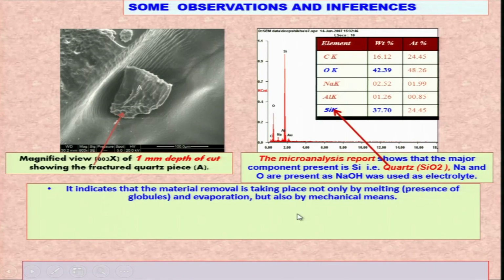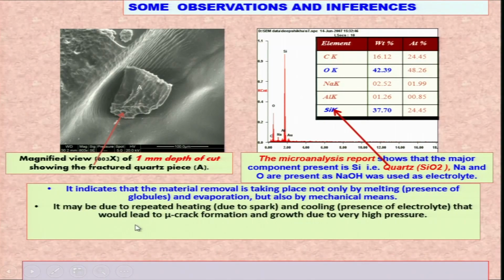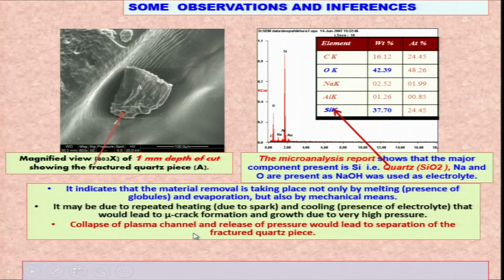It indicates that material removal is taking place not only by melting, which is represented by the presence of globules I have shown you in the earlier slide, and evaporation, but also by mechanical means, that is fracturing, as I have shown over here. It may be due to repeated heating due to sparking and cooling due to the presence of electrolyte, that would lead to micro crack formation and growth due to the very high pressure of the electrolyte. So, collapse of the plasma channel and release of pressure would lead to separation of the fractured quartz like this.